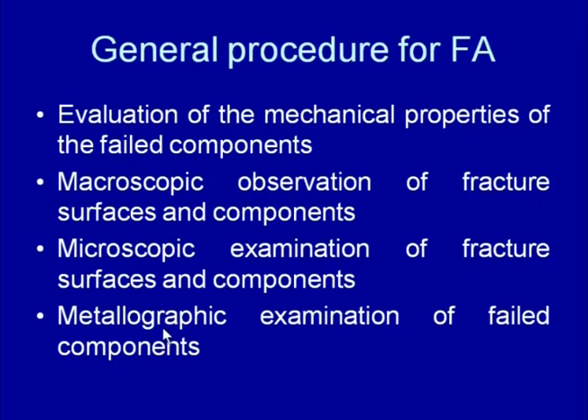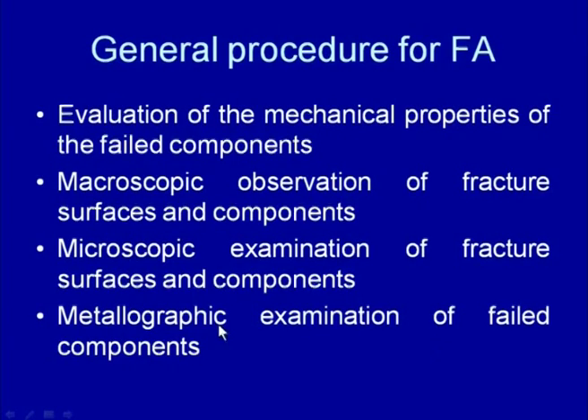Then the metallographic observation of the failed sample is also done, which will show whether microscopic discontinuity is present in the material which has failed, whether the metal was the correct kind or not, whether the manufacturing processes were used properly or not, or whether any kind of adverse effect has occurred in the material during the service, for example, in the form of corrosion, decarburization, grain coarsening, or any other effect which can be there in the component during the service. So, all that can be verified through the metallographic examination.